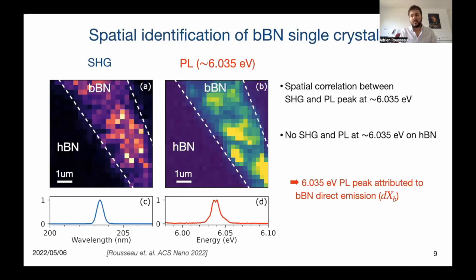By performing second harmonic generation intensity mapping on the area of interest, we observe that the second harmonic generation on the Bernal boron nitride region is very strong, where it vanishes in the hexagonal boron nitride region, as you can see on the image on the left.